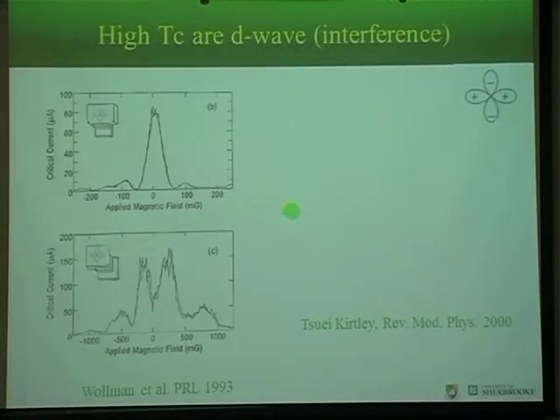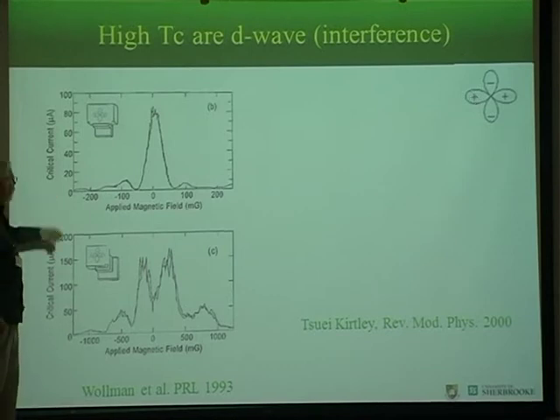Well, so the high temperature superconductors, the first thing to say is that they are D wave. D wave means that the Cooper pair wave function has this dependence, so it changes sign. So there are nodes along the diagonal. And the experiments that showed this the most convincingly are interference experiments.